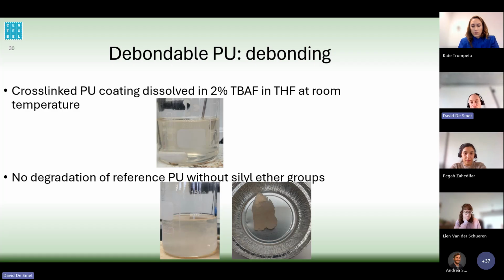While in the pictures below, we actually did the same experiments, but with just a reference PU. Meaning that we didn't use any silyl ether diol in the backbone. We still used the same compound, the same isonate, the same polyol. And it's clearly seen here that the PU does not degrade. You can see that your solution is not transparent, and after filtration you can still see a clump which is remaining, which is still your polyurethane.